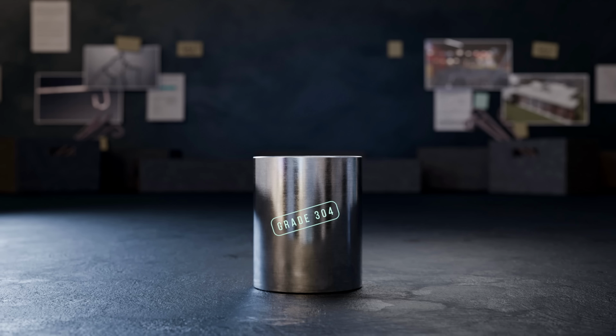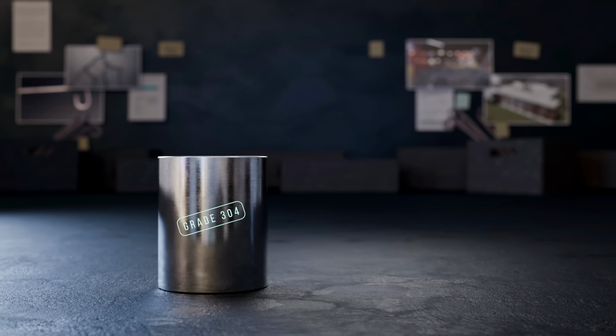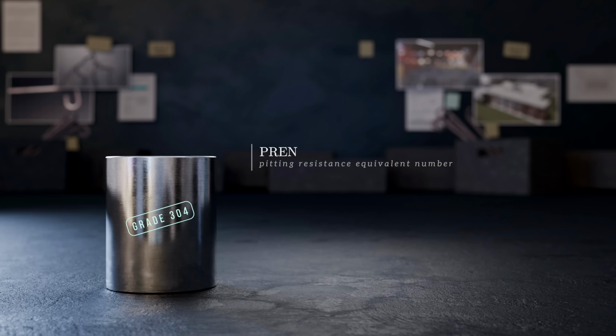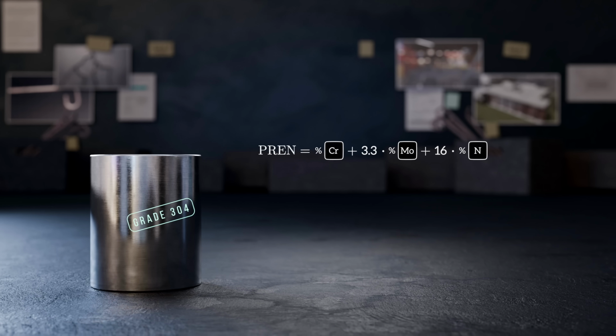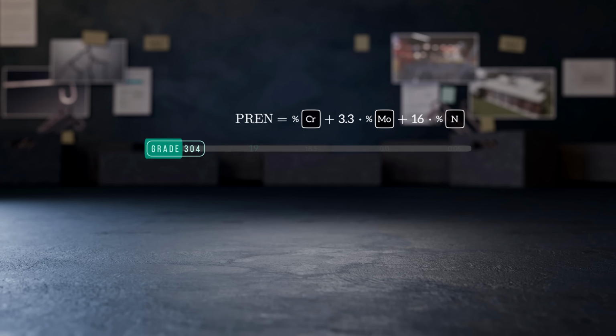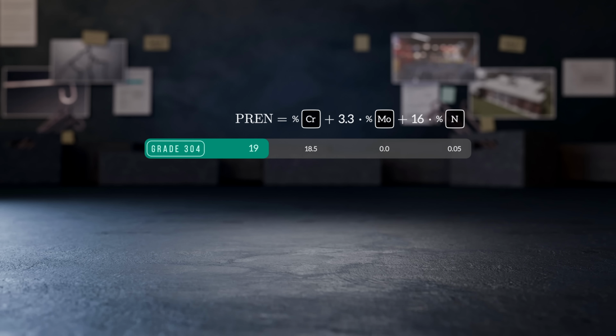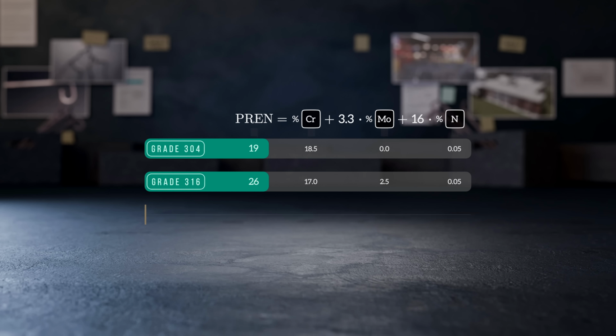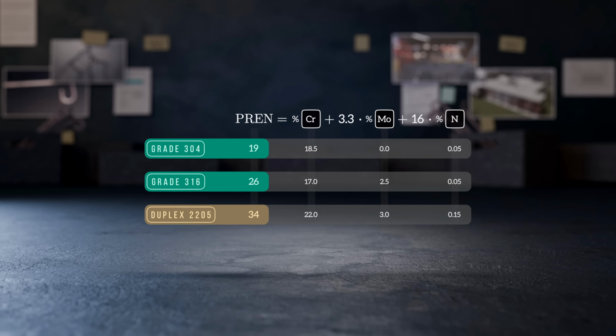A second problem with 304 was its resistance to pitting corrosion in chloride environments. Engineers quantify this using the pitting resistance equivalent number. It's calculated based on the amount of chromium, molybdenum, and nitrogen in the alloy. With no molybdenum and only limited nitrogen, 304 has a relatively low PREN compared to many other stainless steels, making it more prone to the pitting corrosion that can act as initiation sites for stress corrosion cracking.